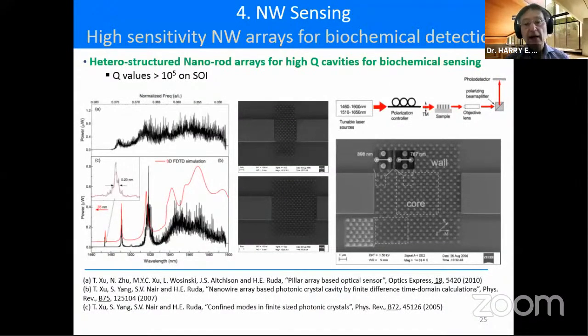All right, so here is the kind of structures that we've been looking at. And the way we did it is we are looking at trying to control adiabatically the way the modes spread in the cavity region, the core region. And we did that just like you do in a traditional fiber optic system, with a wall and a core. And the wall has a different period structure, different spacing structure to that of the core. And clearly the way light propagates in the core will depend, in K-space, will control the group velocity of those various modes we're looking at and so forth.